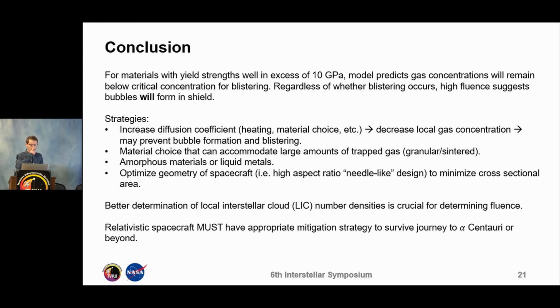So in conclusion, what we take from this study is that materials with yield strengths well in excess of 10 gigapascals will likely remain below the critical concentration for blistering, according to the model's predictions of gas concentrations. However, regardless of whether blistering itself occurs, the high fluence suggests that bubbles will form in whatever shield you make. Some strategies moving forward in designing a shield would be the ability to increase the diffusion coefficient either by heating or by a different material choice. This can thus decrease the local gas concentration and may prevent bubble formation and blistering altogether.